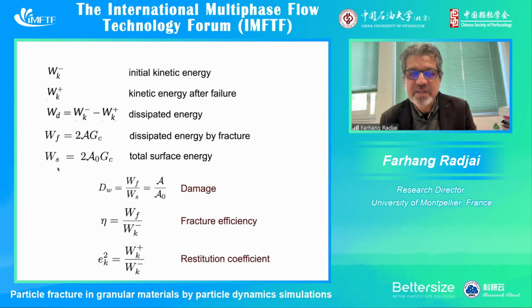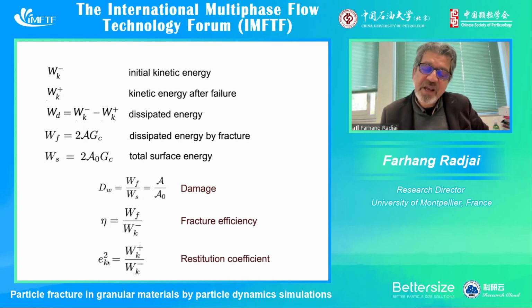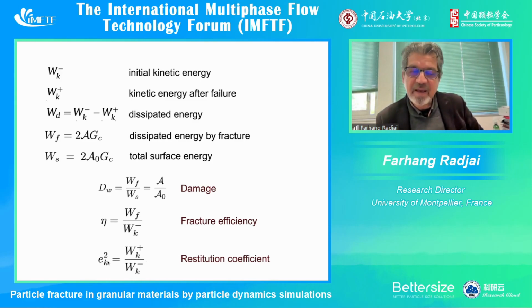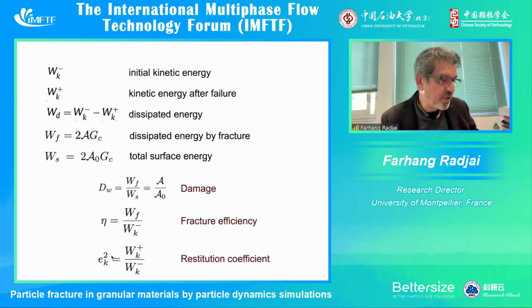So from these quantities, we can define the damage, which is the amount of surface generated compared to the initial surface. Fracture efficiency, eta, is how much of this energy is used for fracture, because the energy is also dissipated by inelastic collisions, by friction, and so on. And the restitution coefficient, which is the ratio of the total kinetic energy after breakage and the impact energy, WK, defines the square of the restitution coefficient.